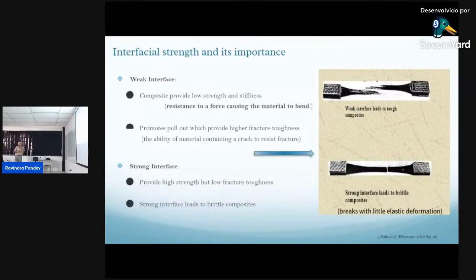The definition which we need to be careful about is how do we define the material. You can see here, the tough composites are where the interface between this fiber and matrix is very, very weak. So when you apply the external pressure, it breaks like that. Then we have the strong interface where we have little elastic deformation as we apply the pressure or external field. So we have weak interface and strong interface, and that's what we have to figure out. Are we looking for a higher fracture toughness or low fracture toughness? The toughness is the criterion a mechanical engineer looks for. How tough the material is.